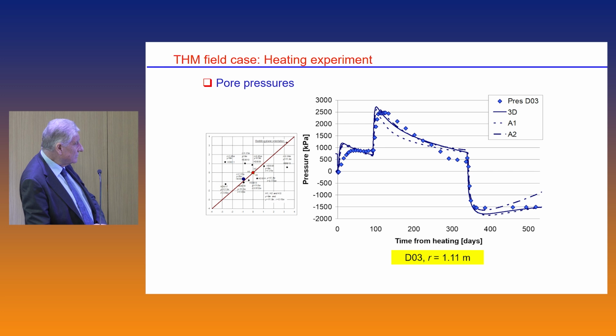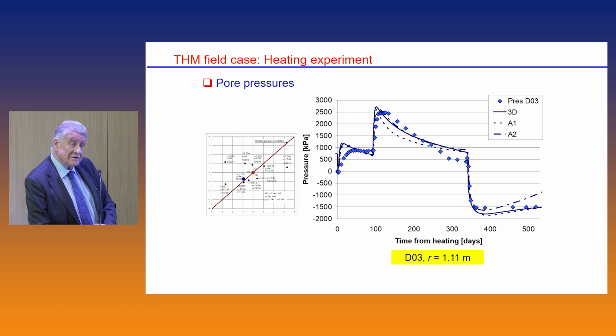And this is the comparison with experiments. At this same point that I was showing before, we can see here that we predict a faster increase of pore pressure than was measured. We feel that perhaps there was some error in the pore pressure sensors, because in the second round, actually, the rate of increase measured and observed is quite the same. Also the dissipation, and also the drop that you get once you switch off the heater.